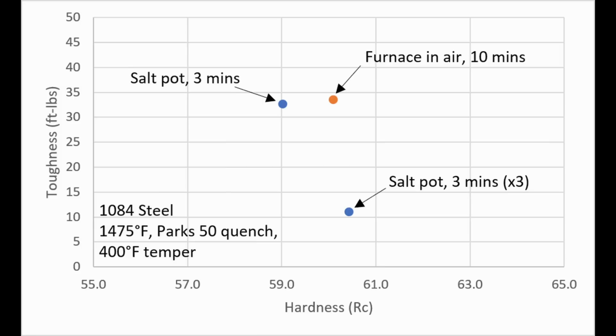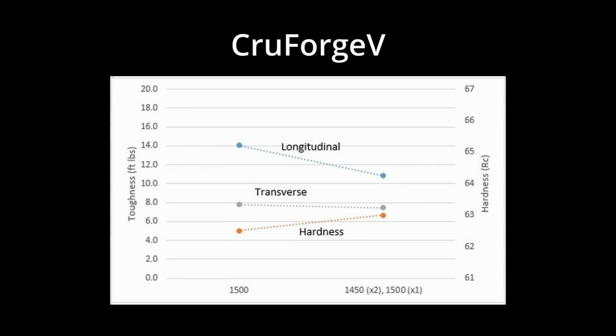And so you need experiments to actually see if you're making an improvement. And when you're getting extra fancy with your heat treatment, you're sometimes in danger. We actually did another triple quench experiment with CruForgeV back in 2018. In this case, we used a conventional furnace, not a salt pot. So with CruForgeV, we did 10 minutes at 1450, then we did that a second time, and then we did the final from 1500. With this experiment, we also saw an increase in hardness and a drop in toughness through the triple quenching. But the drop in toughness was not as extreme in this case.